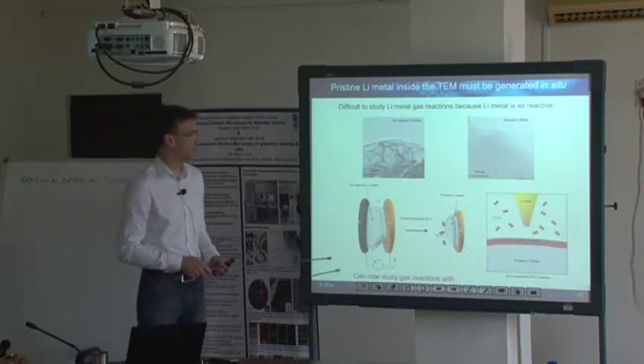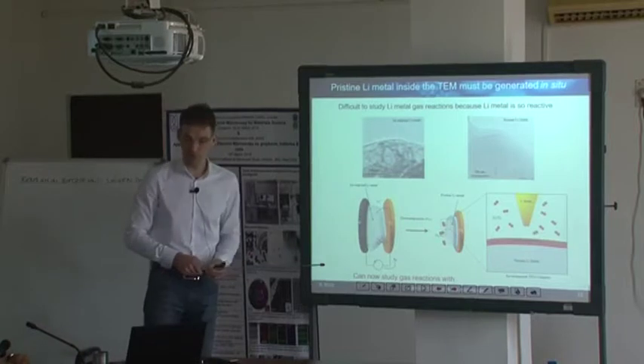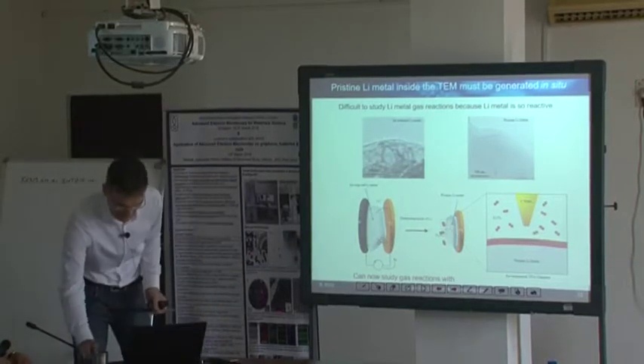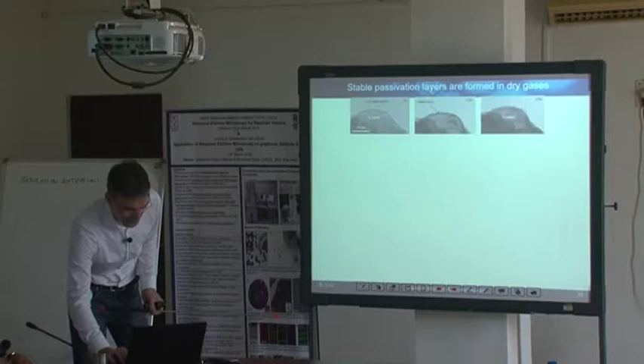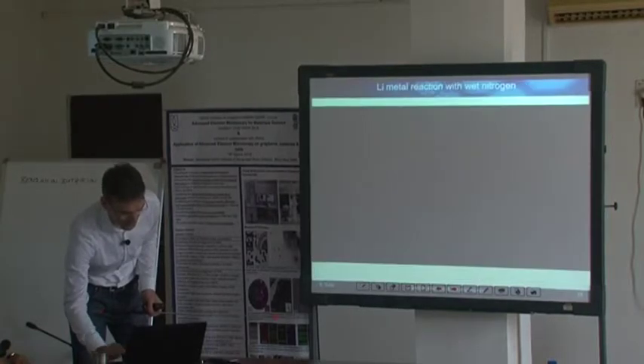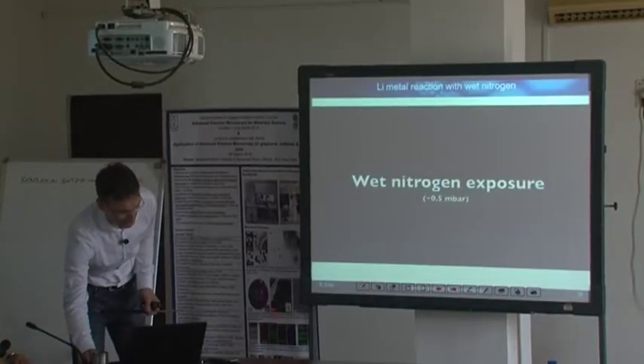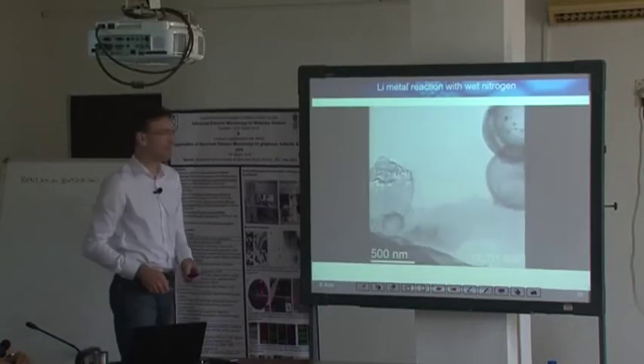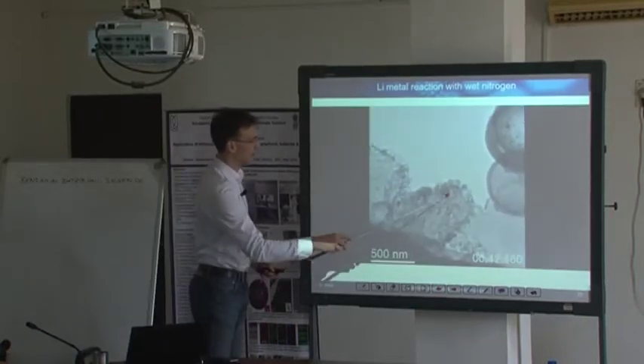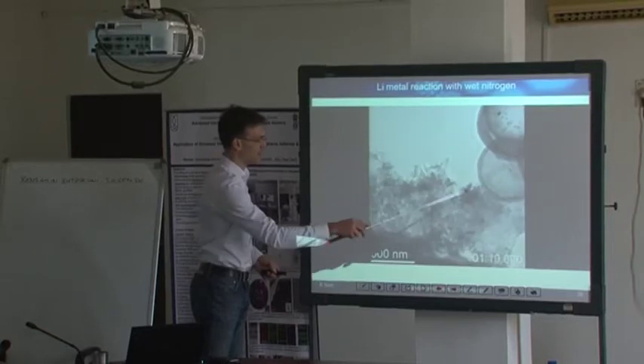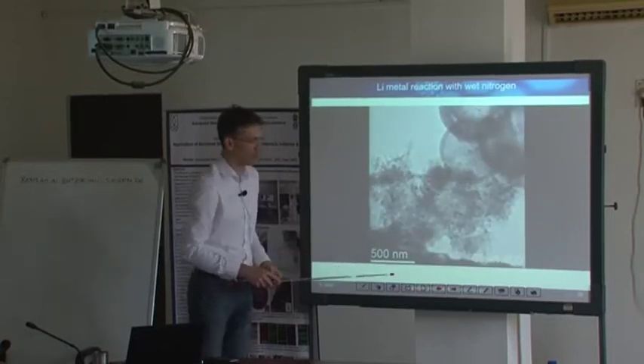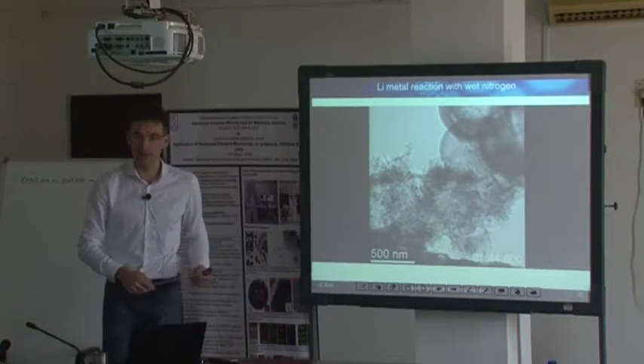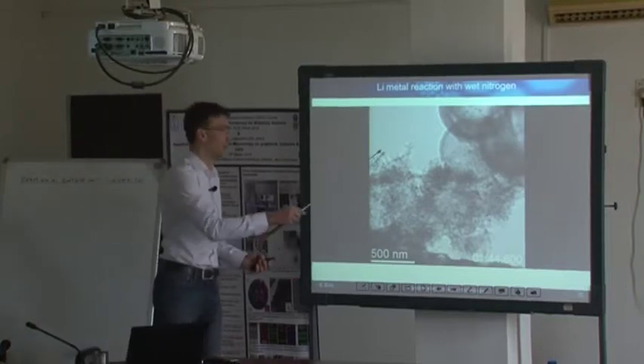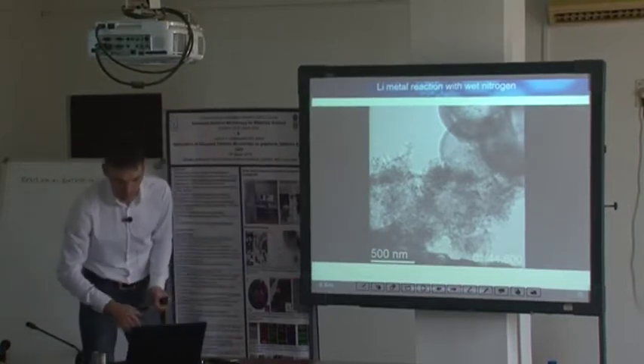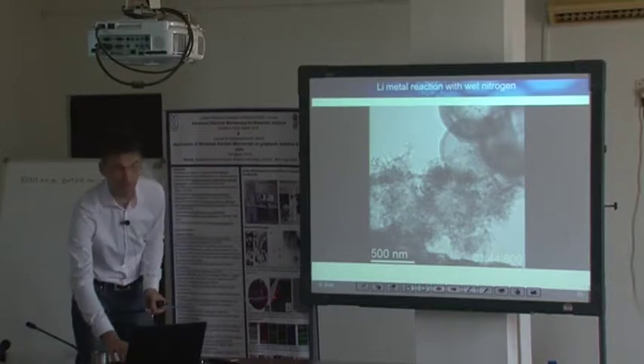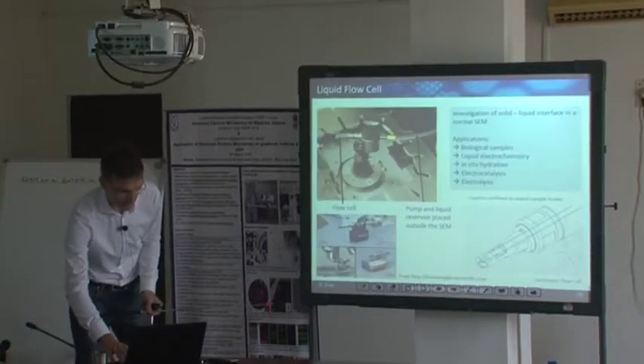This is one example that you already saw. This is the study on the lithium and the corrosion of the lithium, and I will not explain that in very much detail. I would just like to share a second time this corrosion of lithium in wet environment. This is our metallic lithium here, and this is the corrosion layer, which is highly open porous. And by such studies, we were able to understand somehow these reactions going on and causing this drastic degradation of batteries.